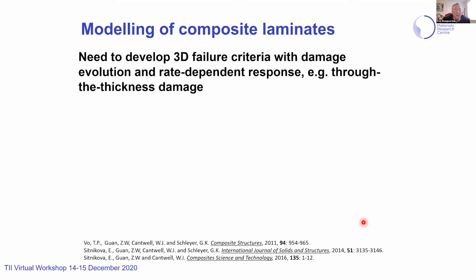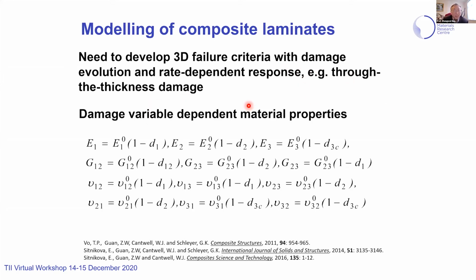In commercial code, you have 2D Hashin criteria. And if you use LS-DYNA, you may have 3D failure criteria, but they don't have control over the damage evolution, rate dependent. So we have to develop a user-defined subroutine, especially for impact and blast, where through-the-thickness damage is very important.